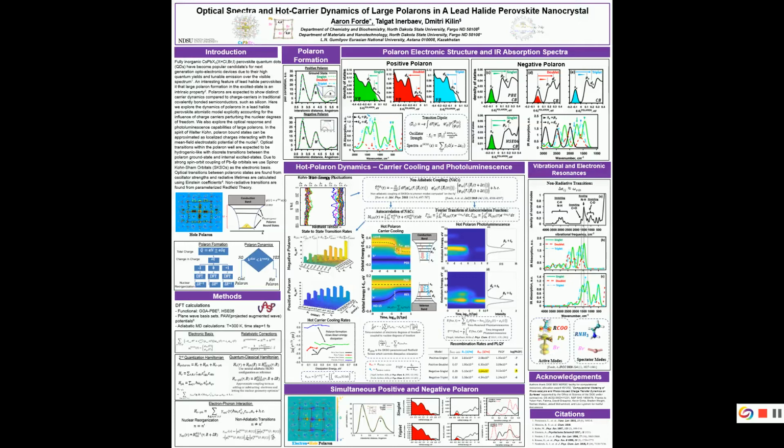And in terms of talking about the dynamics, there are two potential ways that you could think about them. So you put the charge in, and one opposite extreme is that the lattice instantly reorganizes faster than that energy can dissipate. So in that case, you'd have a hot polaron. So our charge would be stuck in the top of the potential well. Or you have the opposite effect where you put the charge in, it gets rid of all of its energy, and then the nuclei reorganize, and that would be a cold polaron. So that would be this charge stuck in the bottom of the well.